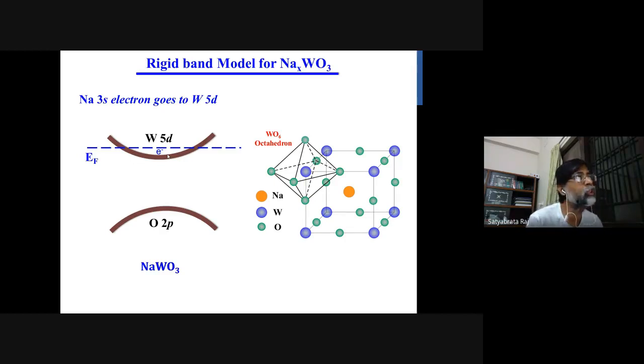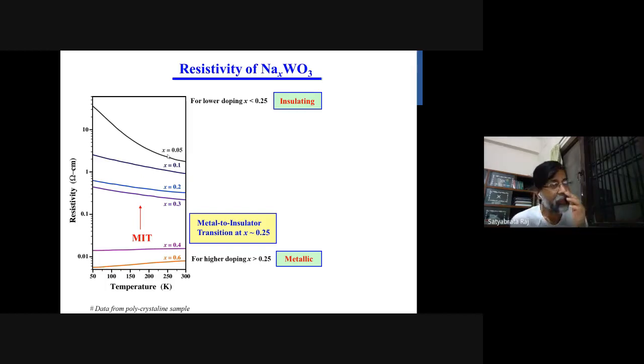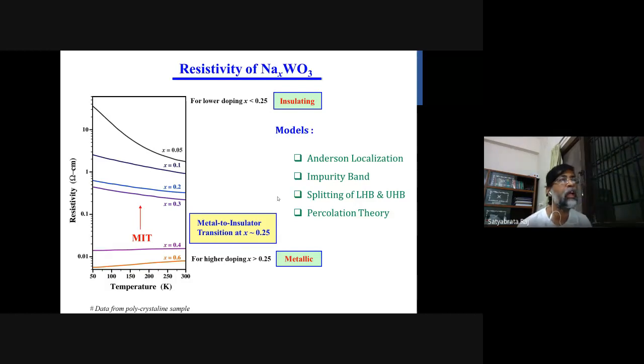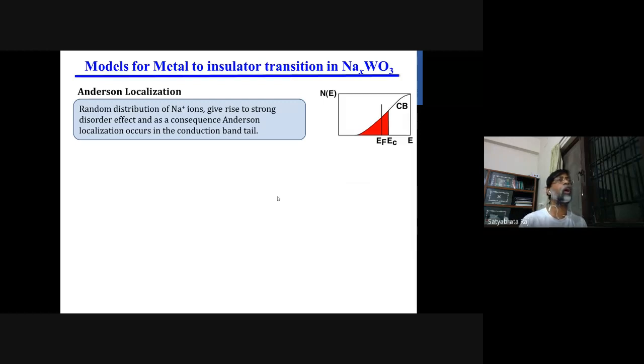But when we dope sodium and measure its resistivity, we found that for a small amount of sodium, though for 0.05 it should be metallic, its resistivity says that it's insulating. This insulating feature continues up to 0.25, and for larger x values it shows metallic features. That means there is a metal-insulator transition somewhere around the 0.25 composition. So the question is, which model is appropriate to explain this metal-insulator transition occurring with the doping. So let's understand what those models are in a little bit more detail.